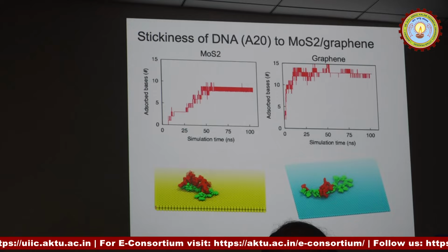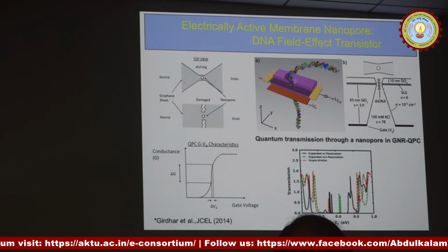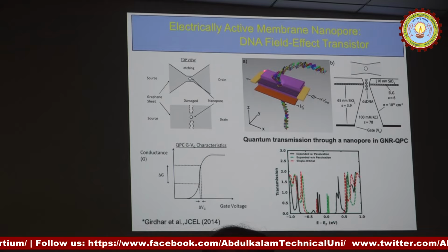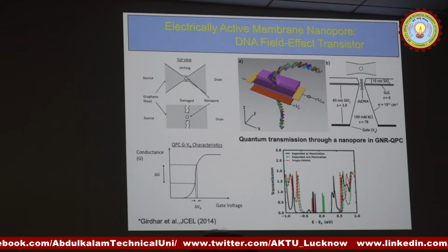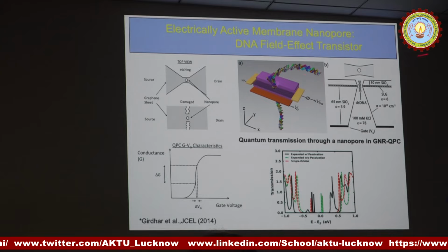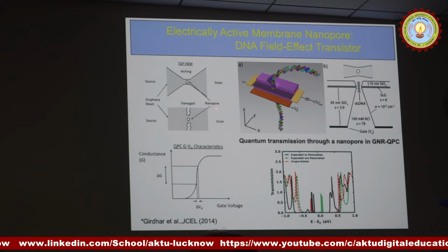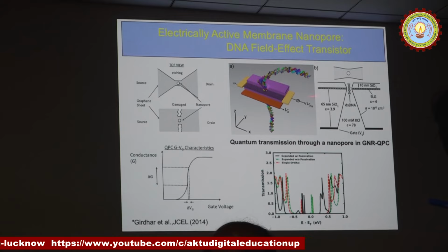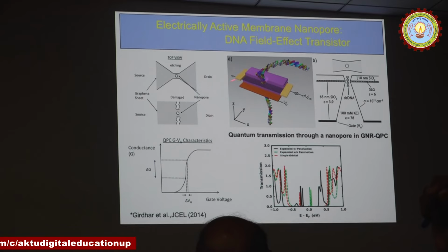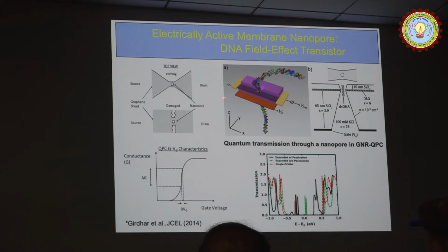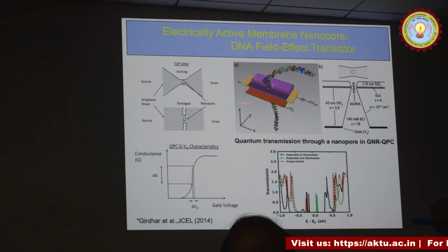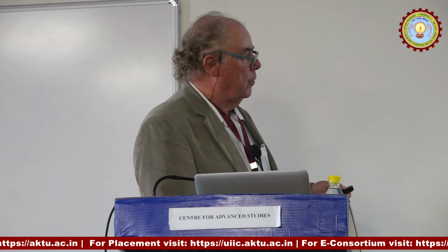Now, I've talked to you about these two materials. What we did some time ago, considering that solid-state nanopores can be used to sequence DNA, is to get one step further. I told you this is electrically active, and what we propose is to make a membrane act as a transistor. So we have this 2D material, sandwiched between two dielectrics, and then putting at some point below it a metallic layer which we would use as an electric gate, to force a current to go along the pore to have better detection. So that's a cross section of the transistor that we propose.